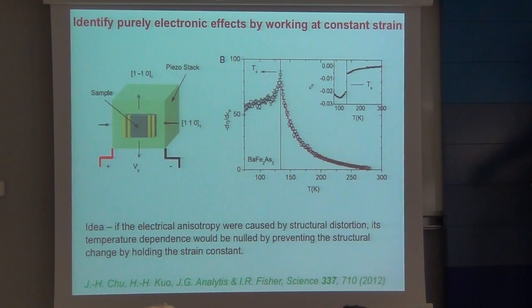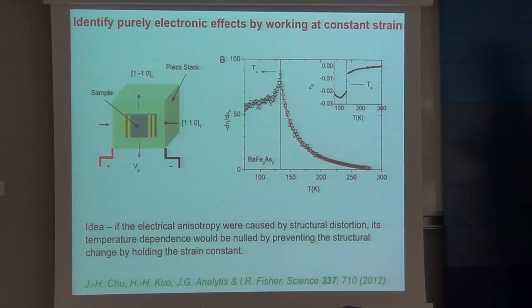And they did this rather nice experiment published in 2012, where they showed a diverging, now this is the resistive anisotropy's derivative as a function of temperature. So they hold the strain constant grossly, and then they wiggle it a little bit, and they see how the resistive anisotropy reacts. And they saw a beautiful lambda-like divergence of the anisotropy heading towards a well-establishable TC, which also actually wasn't exactly the same as the structural TC. Right? And so they were able to prove a lot of things here.